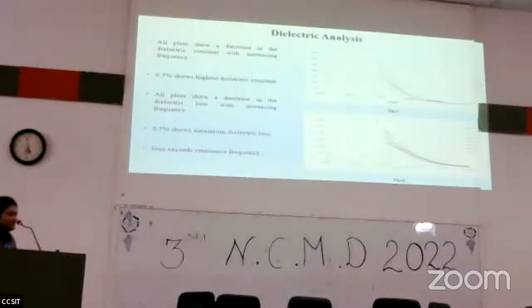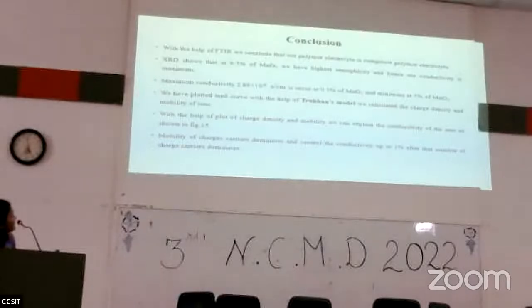After that, I did dielectric analysis, as you can see in the figure. At lower frequency we have the highest dielectric constant, and the lowest dielectric constant at the highest frequency. So I conclude that our polymer electrolyte is a composite polymer electrolyte. XRD shows that 0.5% MnO2 has the highest amorphicity, and hence our conductivity is maximum. Maximum conductivity is 2.89 × 10⁻⁶ S/cm. We plotted the curve with frequency, and with the help of Trukhan's model we calculated the charge density and the mobility of ions. Mobility of charge carriers dominates and controls the conductivity up to 1%, and after that the number of charge carriers dominates.